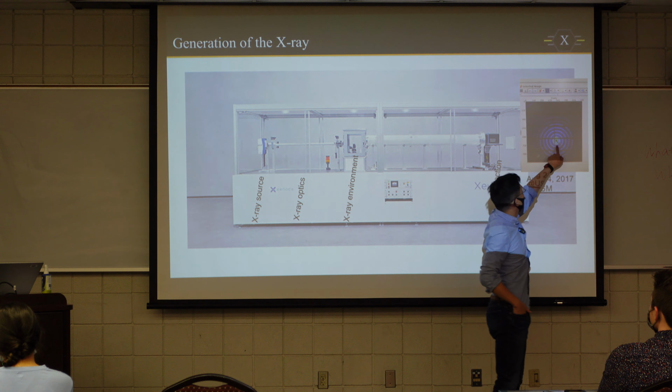The lowest scattering angle is defined by the beam stop, because we always need to block the direct beam. It's so intense that it's going to either destroy your detector or overpower your signal. So we always put a piece of metal to block it. So the smallest angle we can reach is defined by this tiny beam stop and the Q range we can get there.